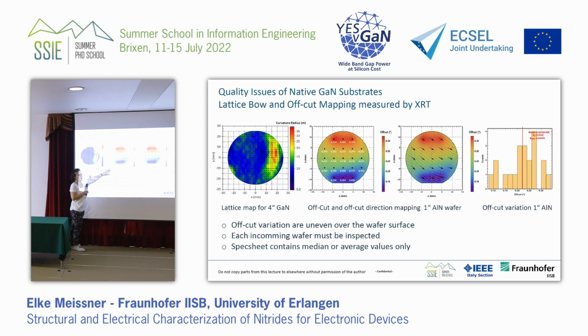So you don't have any chemical mediation here in aluminum nitride growth. It's more difficult balancing the gas flows, for example, in an HVPE process like this was done for that crystal. So it's much more difficult, and this is what I said at the beginning. The choice of the crystal growth process initially tells you how good you can achieve perfection in the crystal. If you have no other choices, of course, because your material is not growable as a crystal with another than this method that you have chosen, okay, then you're stuck with that. Then you have to make the best out of it.